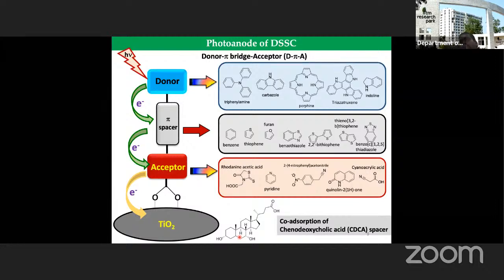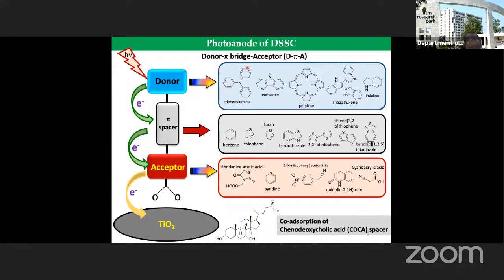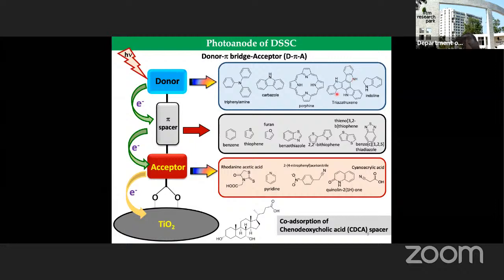This is mainly used to avoid dye aggregation in the solid state, because otherwise the pi bonds present in the aromatic moiety of the donor generally have a pi-pi interaction with the molecules, causing an intermolecular pi-pi interaction that stacks the molecules one over the other. But if you stack the molecules or if they aggregate, you may have quenching of the excitons that are produced. That means if you are not able to separate the electron and the hole, you will not be able to harvest the electrical energy that is produced. Therefore, it is important that aggregation is avoided, which can be carried out using CDCA.